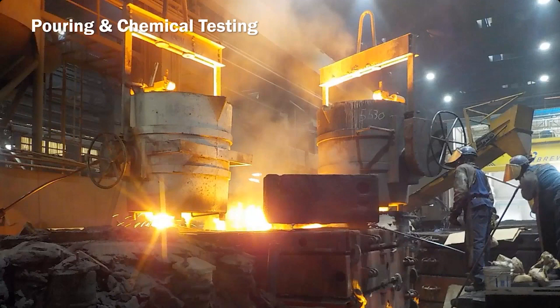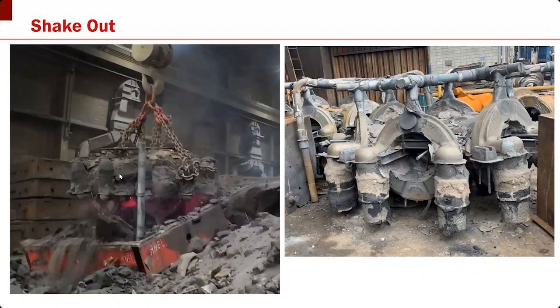And in situ, each time we're doing a pour from one of these ladles, they are doing spectrochemical analysis to check the alloy, and also pouring keel blocks either attached to or pour bars separate. And each one of the destructive examination or non-destructive examination tests that happen along the lifetime of this casting production is tied to the serial number of that unique casting. So there's traceability back to the pour and back to all the testing results.